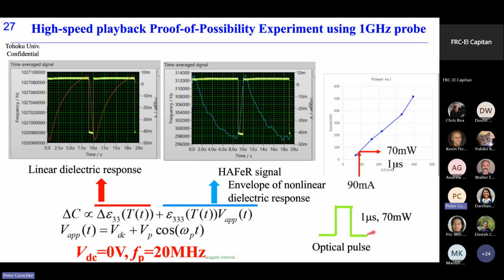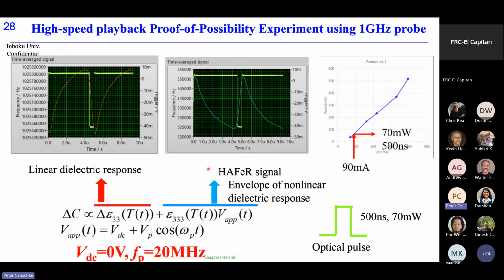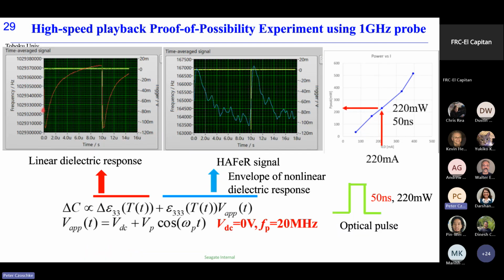In this case, a 1 microsecond laser pulse is applied, and the left one, this red curve, is the linear dielectric response, and the right one is the HAFeR signal or nonlinear dielectric response. And of course, you can clearly see the increase of the signal via laser application. So we reduce the pulse width to 500 nanoseconds, and even at this speed, we can confirm the waveform. But due to the large heat capacity, it has a rather large time constant to cool down.